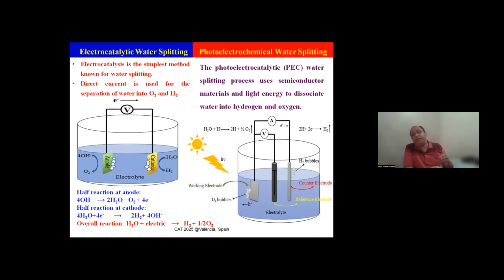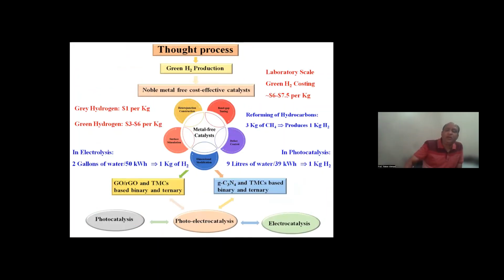So if you make some transformations, like if you use the light source, then kinetically the reaction rate becomes faster. This methodology is then called photoelectrochemical water splitting. This is the three electrode system reaction where you can make the working electrode with the help of the suspension of your material, and then you have to use this methodology to make the process economically viable.